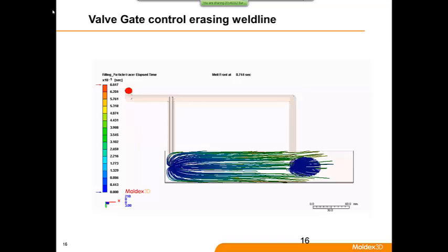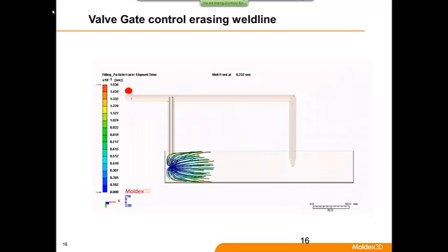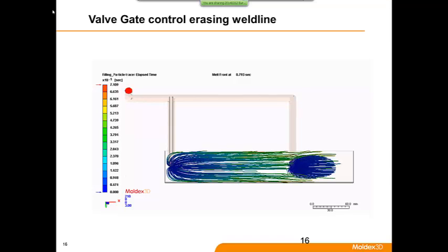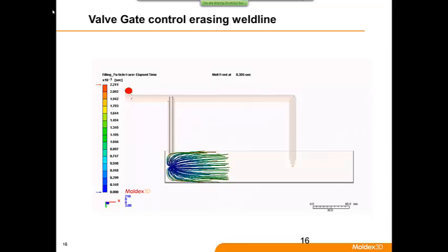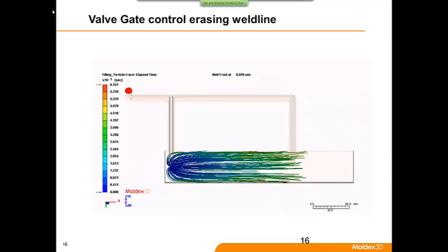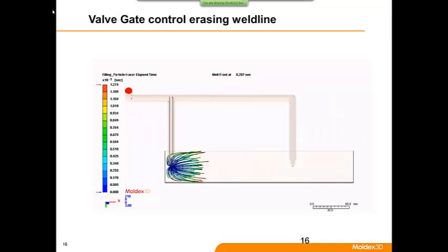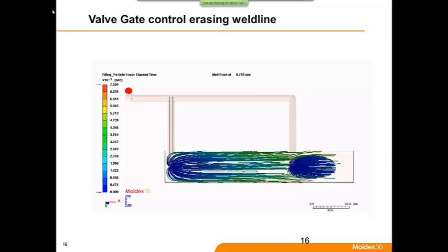So there are a lot of ways, of course, to get rid of weld lines. This is showing one of the examples that Moldex3D can predict. This is a hot runner sequential gating that's been used a lot to erase the weld line. And in Moldex3D, we have this unique feature of showing the particle tracer. You can see on the left-hand side, this hot runner opens first. So you can follow all the particles and make estimations as they pass through your second inlet location.